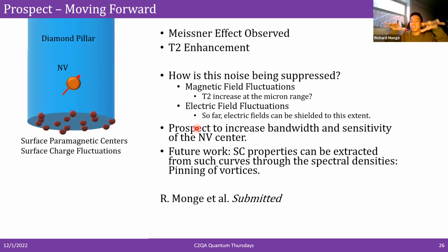And they can also observe the same effect, where if they alter the arrangement of charges at the surface, they can enhance the T2. And that's because they are driving these electron charges away from the surface. So hopefully I answered your question, but yeah, that's my answer.